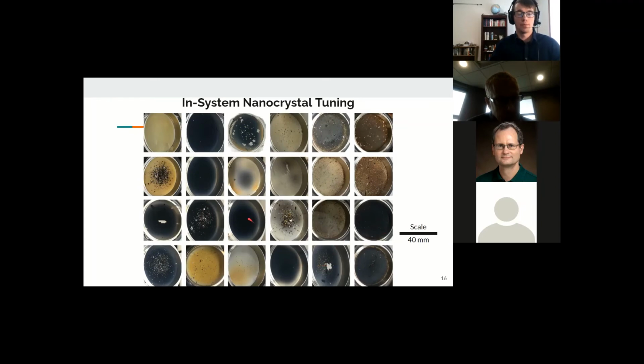The dark powdered samples in this figure indicate an excess of carbon in the powder, while the lighter, yellow colored powders indicate an excess of silicon in the powder. This suggests that it has a similar absorption spectrum to silicon because silicon is also yellow, and we saw that when we actually took the absorption spectra. And this wide variation in color demonstrates the change in optical and electronic properties of the material, and that's mostly based on surface composition.